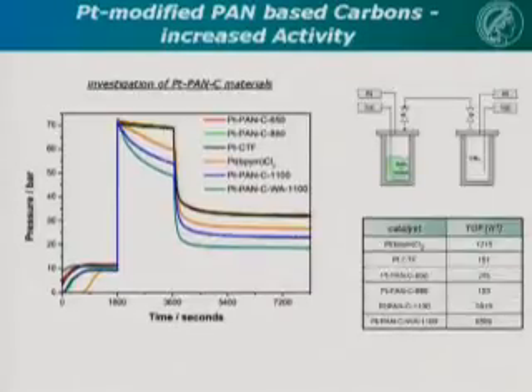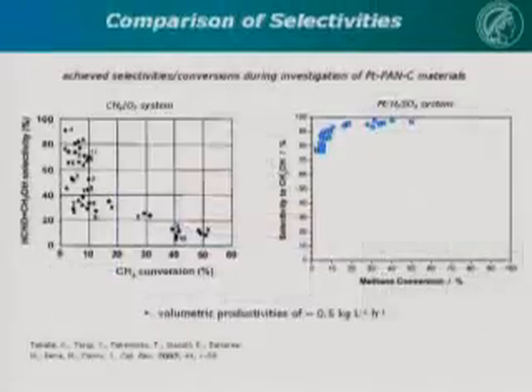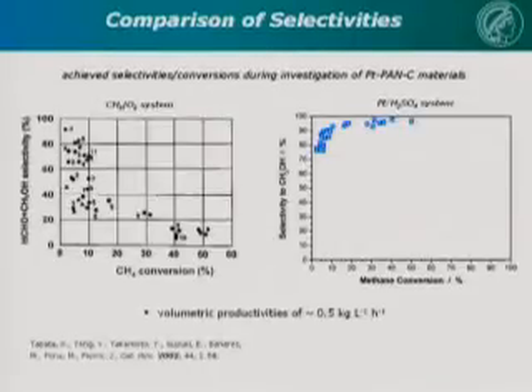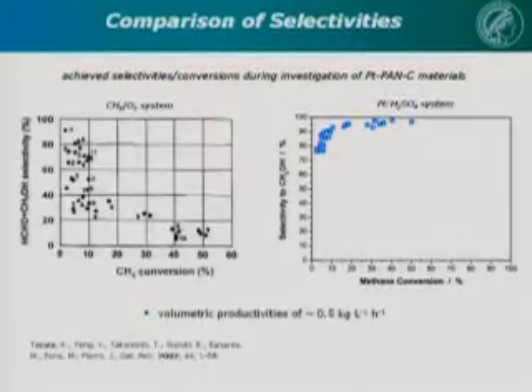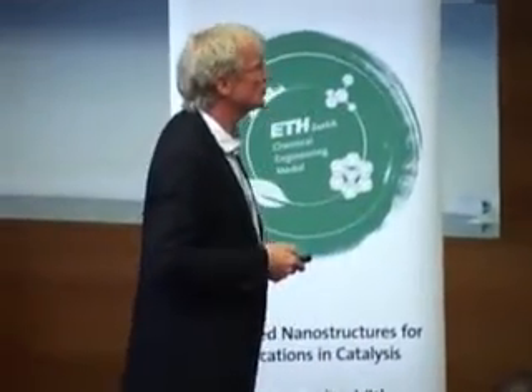And this is now an activity which was set at the time by Catalytica as economically viable. We have calculated this. It's actually productivities of 0.5 kilograms methanol per liter and hour. And this is industrially acceptable. That you can make 50,000 tons per year in a reasonably sized reactor. Several, I think 20 cubic meters is what I calculated.